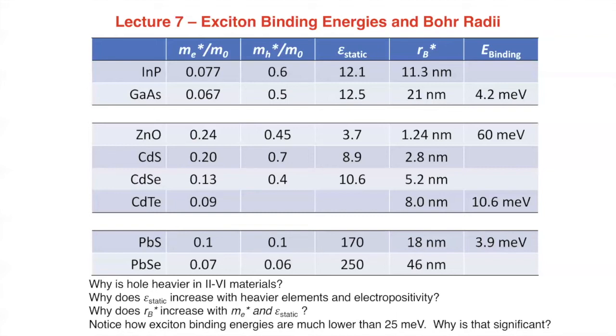All right, so big difference in these materials and the degree to which they can be confined as a function of crystallite size. Something like lead sulfide and lead selenide feels confined even when you have relatively large nanocrystals. So a 10 nanometer nanocrystal is a relatively large crystal. And if that crystal is formed from lead sulfide and lead selenide, you're going to see strong confinement. If that crystal is cadmium sulfide, you're not going to see any confinement because the excitons are smaller than the crystallite size.